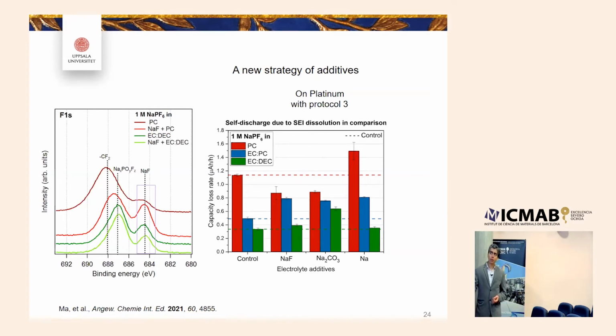On the other hand, we didn't see such a thing with sodium carbonate. This is still puzzling. We didn't see any advantage of sodium carbonate in the PC electrolyte, and our conclusion from this result was that we don't expect sodium carbonate to be present in the SEI from the beginning. So the addition of such species didn't really help to saturate the electrolyte or decrease the SEI dissolution. But this is a strategy for us to try to mitigate the SEI dissolution.